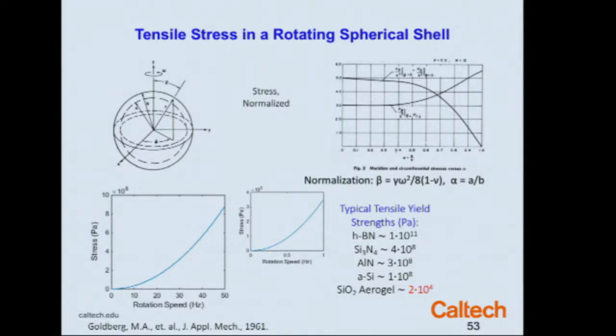So we decided to make an analysis. Say we had a structure the size of a light sail that was, say, a disk or a sphere. What rotational speed could it get to before the material at the edge of the sail exceeded the tensile yield stress of the material? Here are some typical tensile yield stresses for boron nitride, silicon nitride, aluminum nitride, amorphous silicon, and so forth, in the range of 10 to the 8 to 10 to the 11 pascals. That tells you I could tolerate rotation of the sail, for the diameters we're talking about, a few square meters, up to a few tens of hertz or so. You wouldn't want it to rotate faster than that for fear that you would compromise the tensile strength. At least that's my picture of this.